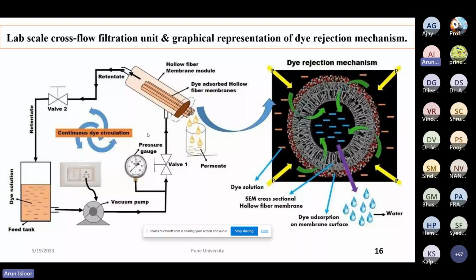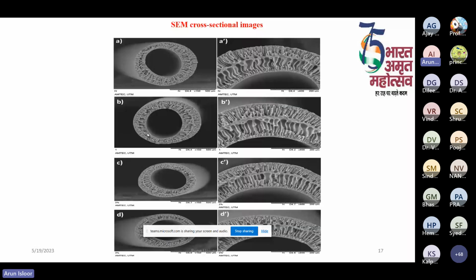This is a cross-sectional picture of a typical hollow fiber membrane. On the right side, you can see the inner core. The dark colored core is completely hollow, and the outer region is highly porous, through which the percolation of the fluid takes place. This is the cross-section of hollow fiber membranes fabricated in our laboratory. In the next 8 or 10 years or so, I strongly believe that flat sheet membranes may be completely replaced by hollow fiber membranes, because they have many advantages.